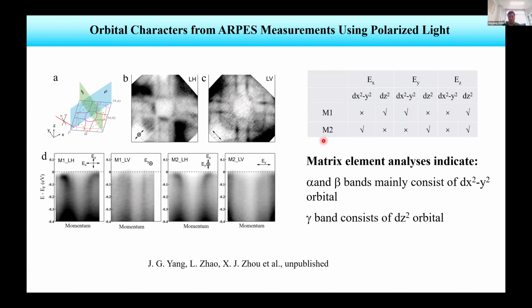I shall say the conclusion: for the alpha Fermi surface and beta Fermi surface, they are consistent with the dx square minus y square orbitals. And for the electron states near the pi points, that's mainly the gamma band, which is consistent with the dz squared orbital. So from the polarized light measurements, we can determine the orbital characters of the observed bands.